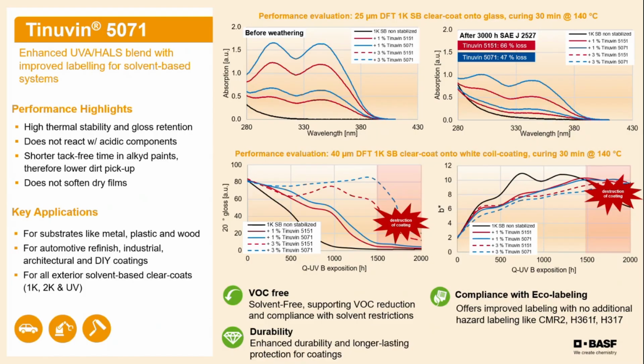We won't go through all the graphs, but we will leave them for your review. But if you look at Tinuvin 5071 versus, say, a standard product like Tinuvin 5151, at the same level of application and the same coating thickness, you can get improved absorbance, retained absorbance after weathering, in addition to improved gloss retention not only at 20 degrees but also at 60 degrees. And then also your coatings after or during weathering will yellow less.